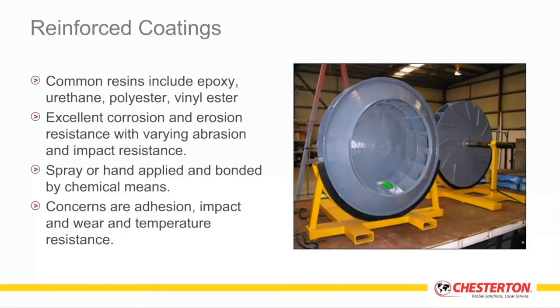And the last category of coatings that we'll look at are what we call reinforced coatings. Normally these include a thermoset chemistry such as an epoxy or a urethane. It may also incorporate polyesters and vinyl esters for high chemical and higher temperature resistance. But normally the epoxy is the matrix that is used, or the binder, and then the functional reinforcements for these